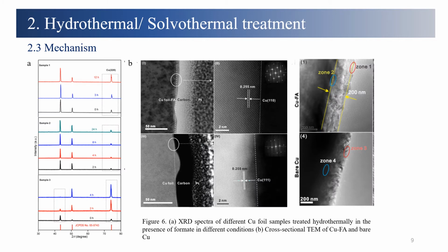So why can this treatment induce the passivation? Surprisingly, regardless of which treatment system was used and which original crystalline orientation of the polycrystalline copper foil was selected, the relative intensity of the copper 110 diffraction peak increased with time. This indicates that deep lattice reconstruction of the copper surface took place during the formate treatment, and we can draw the conclusion that copper 110 formed with a thickness of 200 nanometers, and the untreated copper remained copper 111.